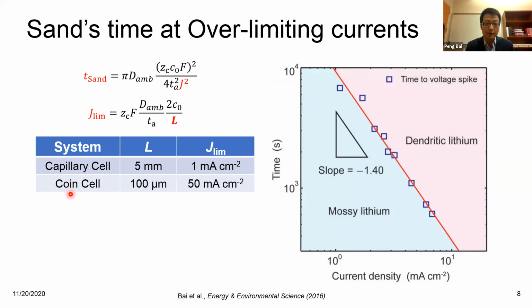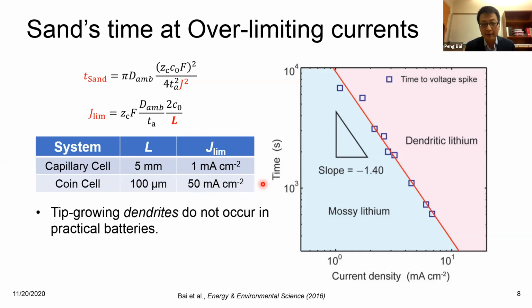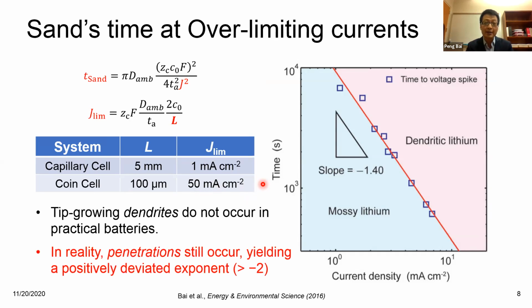But in reality, in a coin cell, when the electrode distance is around 100 microns or even smaller, the limiting current is much larger, closer to 50 milliamps per centimeter squared. That basically tells us that in reality, you should not have tip-growing dendrites in your battery. It won't occur because you won't reach that high current density to trigger diffusion limitation. But what's very unfortunate is that penetration still occurs, right? You won't generate those structures that can go through the separator, but penetration still happens.